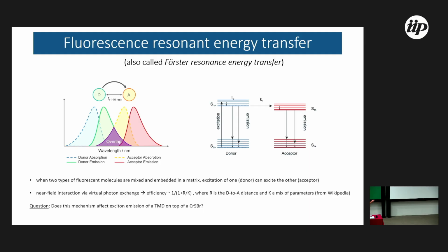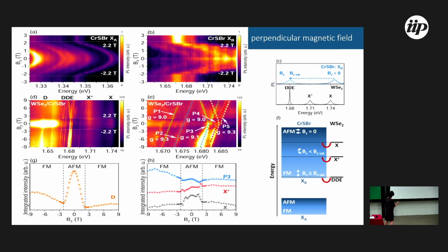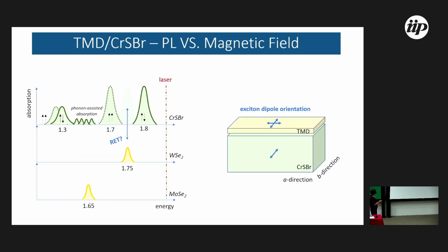There are several types. There is Förster resonance, a dipole-dipole interaction, but there is also Dexter, which is overlap of wavefunctions, and this is well known to people that work with optics in different systems. So this explains the result that I observe here, but I will not have time to go into detail. Why didn't we see this before? Because MoSe2 is far from this B exciton, and in MoSe2 all emissions are around here. So if it's shifted with magnetic field, you can have a resonant condition, which can give the result I showed you.